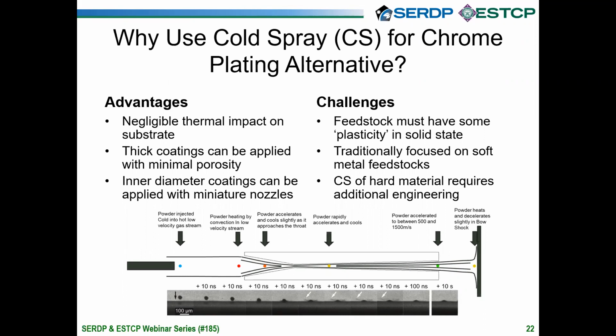Now we call this cold spray, but we're actually heating up the gas stream by as much as 900 degrees C. The reason we call it cold spray is because we keep the particles below their melting temperature. So when they impact the metal surface, they're in solid state. And the process is primarily kinetic energy driven as opposed to thermal energy driven. So the solid state nature of the process gives us certain advantages. Mainly, there's negligible thermal impact on the substrate, and we can build thick coatings with minimal porosity.